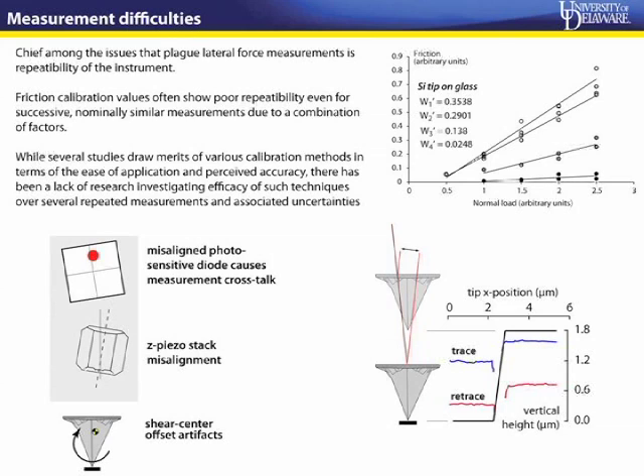Almost all the methods treat calibration as a separate step from the actual measurement. You calibrate an AFM tip, an AFM cantilever, in one step, and then you go down to making measurements with that calibration constant. So you can imagine if you have uncertainties like the position of the piezo, or if the cantilever chip is mounted differently, or any change in the optical path length of the laser within the AFM, those calibration constants that you obtain during the calibration step may not necessarily be applicable or accurate for the actual friction measurements.